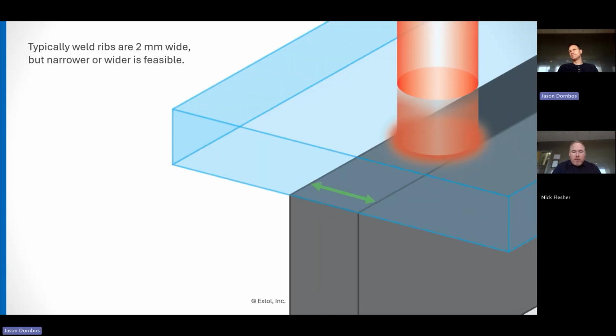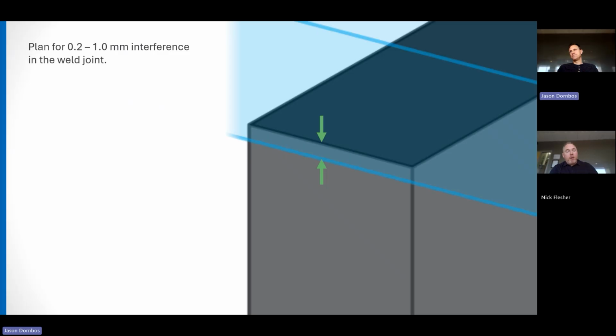I think I've touched on this a little bit. Okay, so this is good. I'm sure a lot of folks are thinking, you've shown me some general weld guidelines, and we've got more coming, but we typically advise planning for an interference of 0.2 to 1 millimeter in the weld rib. We have welded as much as 1.5, but with laser welding, that's actually a lot. With vibration welding, you really have to get the friction going, and people just hammer the parts. If you have to use laser welding based on those 3 criteria we said, typically we're using 0.7. So you're going to use a little less plastic. It's cleaner because there's less of it. Plus, it melts better. So that's what we often see.